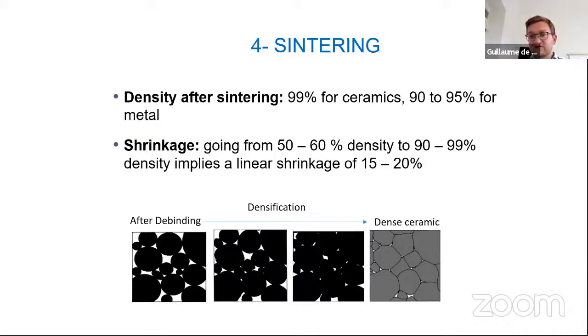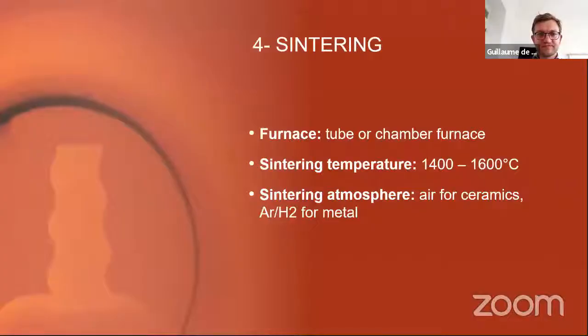The porosities need to go somewhere, or the material needs to go somewhere, and that means you need to have a shrinkage. And usually it's a linear shrinkage of 15 to 20%, depending on the material. Importantly, it's a relatively homogeneous shrinkage in the three directions. So then there's sintering. Sintering is done in a tube or a chamber furnace with sintering temperatures, which usually range between 1400 and 1600 degrees C.